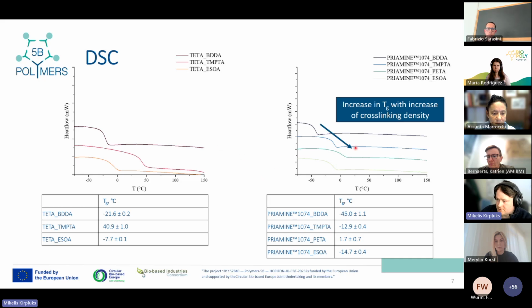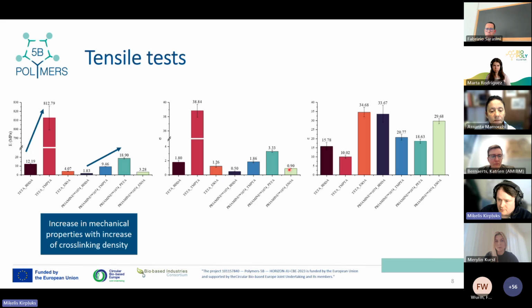So here we see in the DSC experiment that by increasing the cross-linking density of the network, the glass transition temperature also increases. And the same goes for the tensile strength tests. Increasing the cross-link density of the material will increase your tensile strength. And this is something that is typical for polyurethanes.